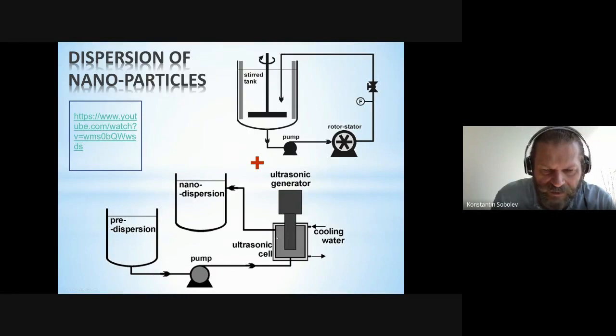Obviously, it is not that all the material is dispersed continuously at that time, so you need to do some sort of circulation. Cooling is something which you need to pay attention to, because higher temperatures may result in agglomeration of the nanomaterials. So instead of dispersion, you may reach agglomeration, or initiate some sort of reaction. So you need to be very careful in dispersion as well.